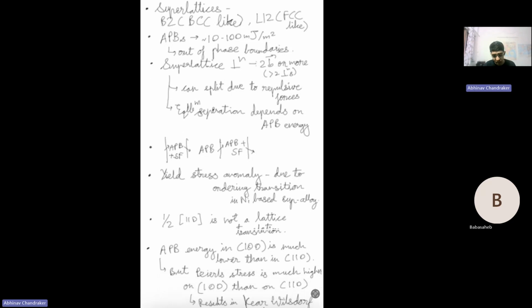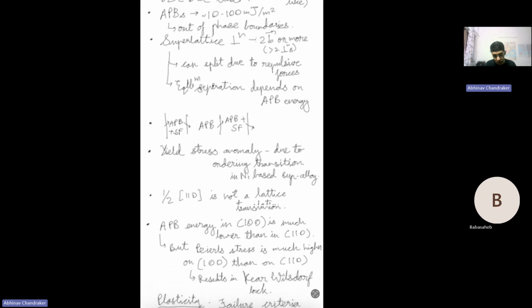So in such cases, instead of single dislocations, superlattice dislocations exist, which basically are two or more dislocations which move together in the ordered phase, so that the overall energy is lesser than what it will be for separate dislocations. Basically, the idea is that if you have two dislocations, it will form less of APBs compared to just one dislocation. But since dislocations will repel each other, they will also split. So there will be an equilibrium separation at which the two dislocations will be. Because of that equilibrium separation, as in the case of partials, dislocations will split into partials, as well as have a separation between each other.